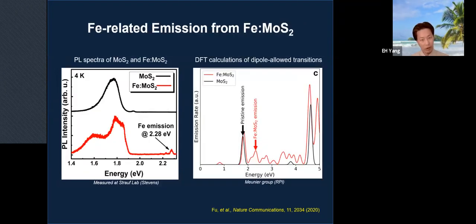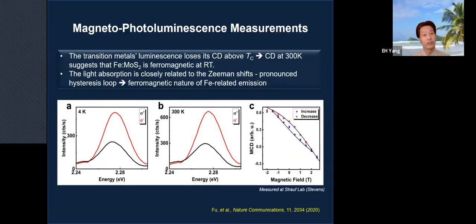Now, this iron-related emission, 2.28 eV, was further scrutinized using the magneto-photoluminescence measurement. So figures A and B show circular dichroism, excuse me. Basically, these transition metal luminescence depends upon left-handed and right-handed circularly polarized light, and their absorption is different. But this transition metal luminescence loses its circular dichroism above the Curie temperature. So the thing is, you see the circular dichroism from this B, right? And that's at 300 K. So it suggests that the iron-doped molybdenum sulfide is ferromagnetic at room temperature.